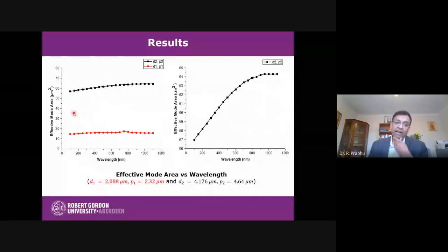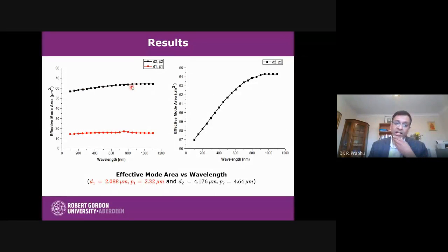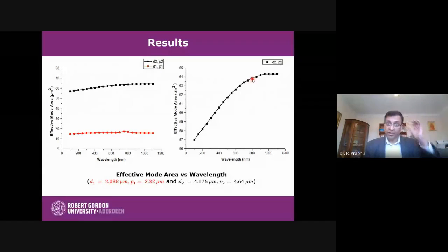Again, she was trying to understand effective mode area, which might result in a stronger signal. As we increase the diameter and pitch, the effective mode area was increasing. That can result in a larger signal from the sample. And it's the same expanded here. You can see the effective mode area for our laser, around 785 nanometers, was higher as a function of the wavelength. So our laser was somewhere here, so we should get more signal. Still, this project is ongoing and more results will be coming up soon.